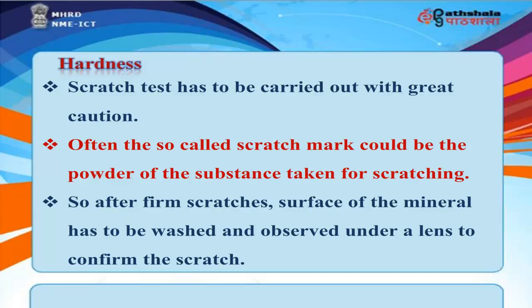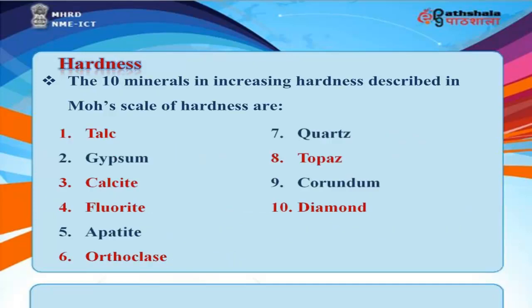Scratch test has to be carried out with great caution. Often, the so-called scratch mark could be the powder of the substance taken for scratching. So, after firm scratches, the surface of the mineral has to be washed and observed under a lens to confirm the scratch. The 10 minerals in increasing hardness described in Mohs scale of hardness are talc, gypsum, calcite, fluorite, apatite, orthoclase, quartz, topaz, corundum, diamond.